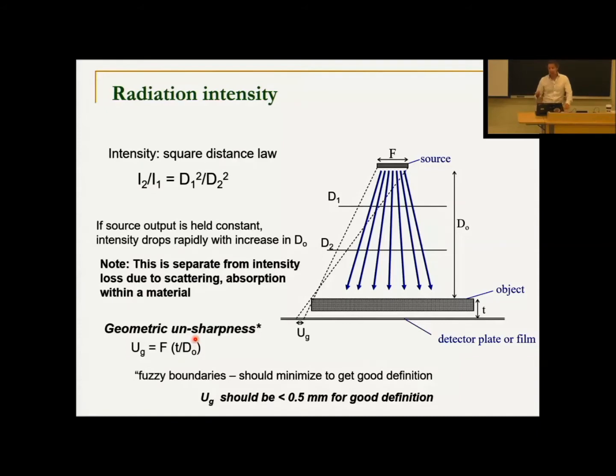We can define this sharpness, how sharp, how defined this image is, and we see from this ratio, we want to minimize this number to have a nice sharp image, and usually we want that number to be less than 0.5. That means kind of the fuzziness or uncertainty in your image. We want that to be low so that we have a sharp image. But to do that, we have to have large D_o relative to t, right?